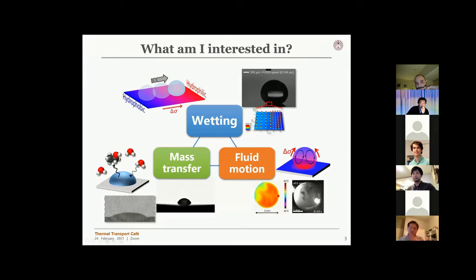First, I have studied the wetting problem with droplets. We fabricated a surface which contains a contrast of wettabilities. We have micropillars with stepwise, different micropillar patterns. If I place a droplet at the boundary between those two different patterns, we can see how the droplet moves. Obviously the droplet moves from the hydrophobic side to the more hydrophilic side. We closely looked at how the droplet walks to the surface which has a lower contact angle.